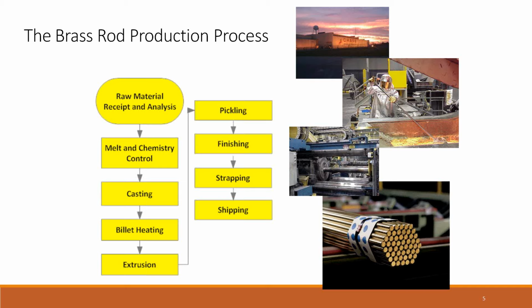Just because it's brass scrap doesn't mean that it can be efficiently processed through the mill if it comes in what we call a giant bird's nest, which creates handling problems. Or it could be really wet, and that can be an issue in chip melting or melt control in the melting furnace. So we sort all those out, and then whatever passes goes to our melting operation. And once everything is melted, chemistry samples are taken, and from that you determine what you need to correct in one of the elements, if any, so that you are within either ASTM limits, or if you've got tighter internal limits than ASTM allows in order to make your castings.